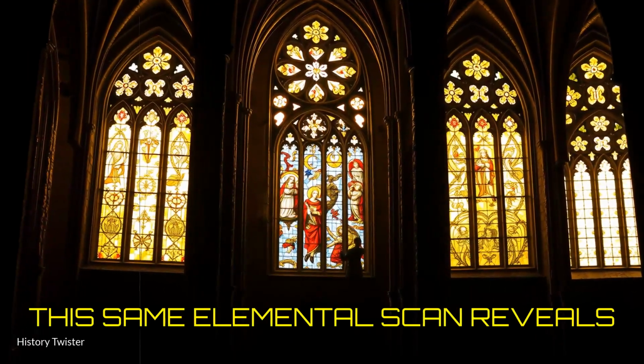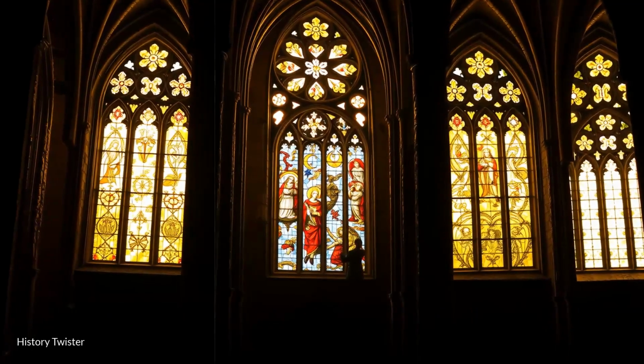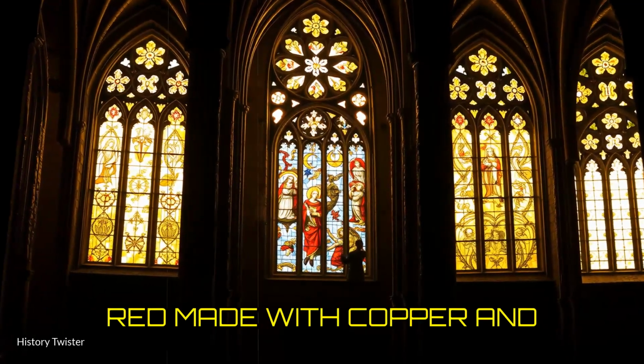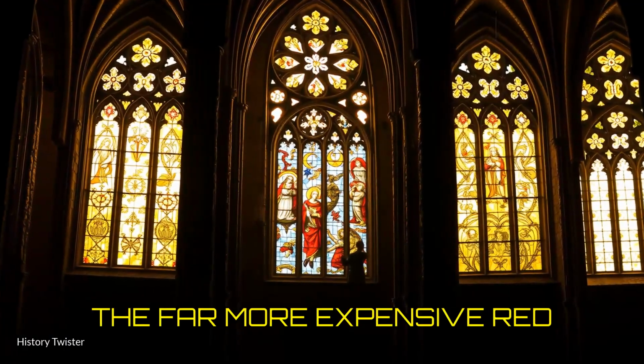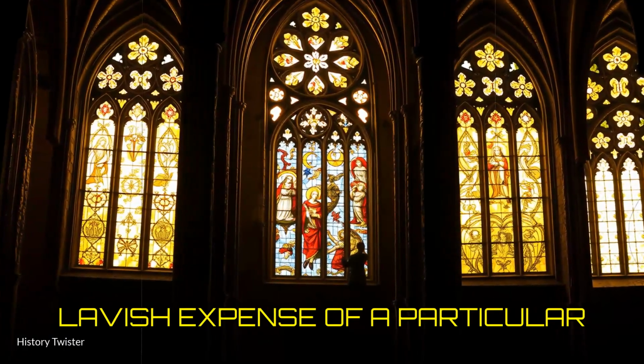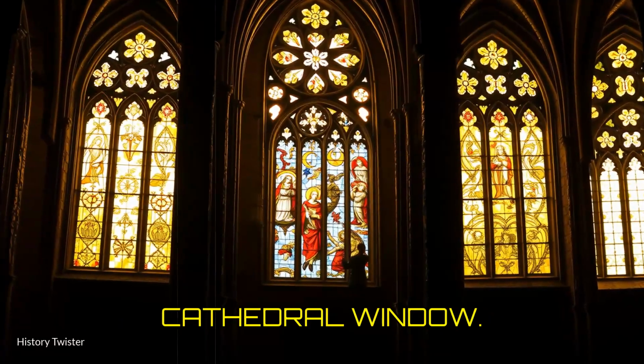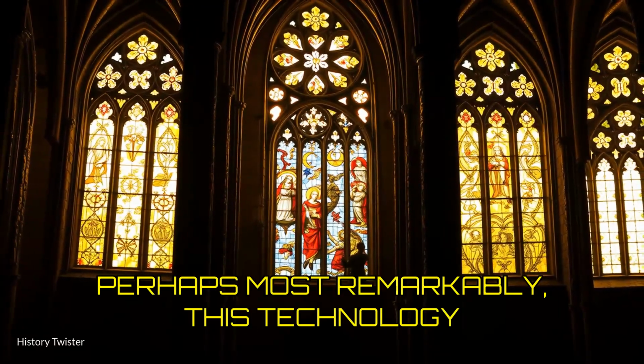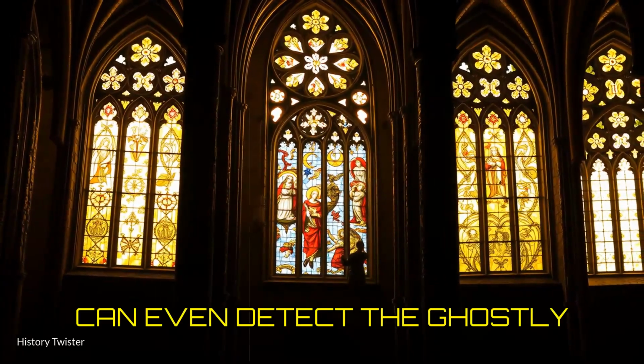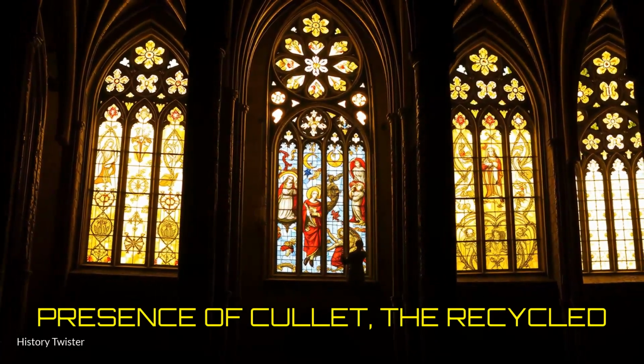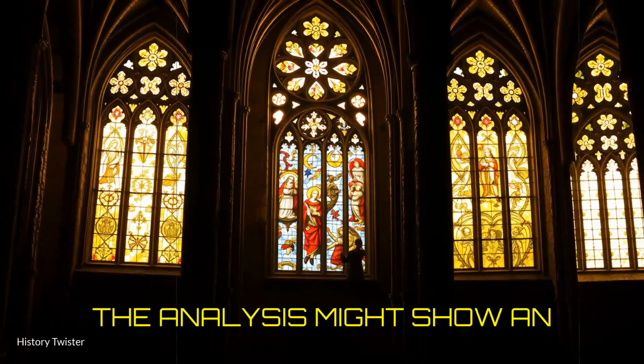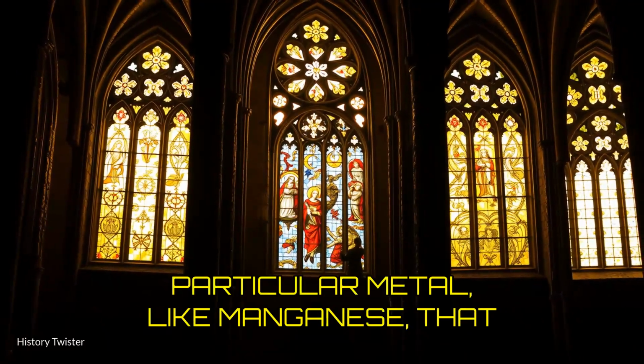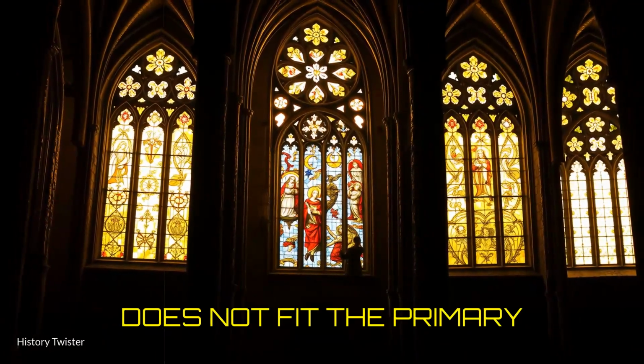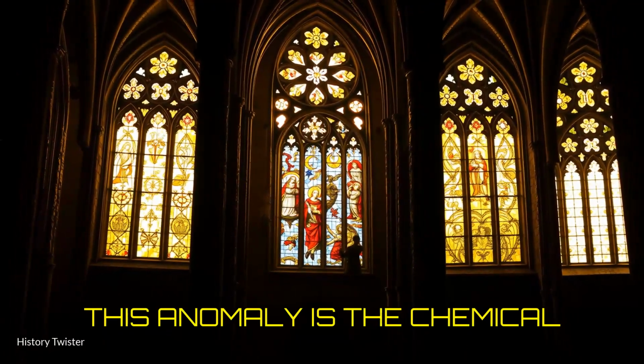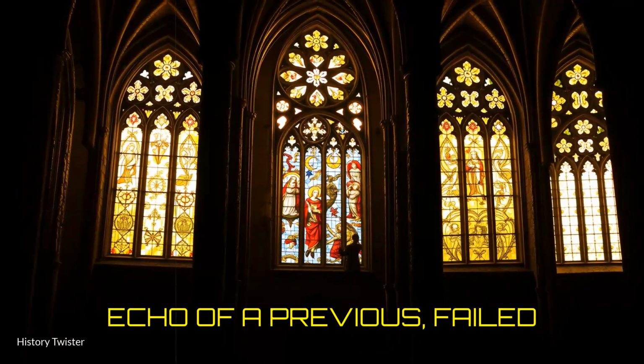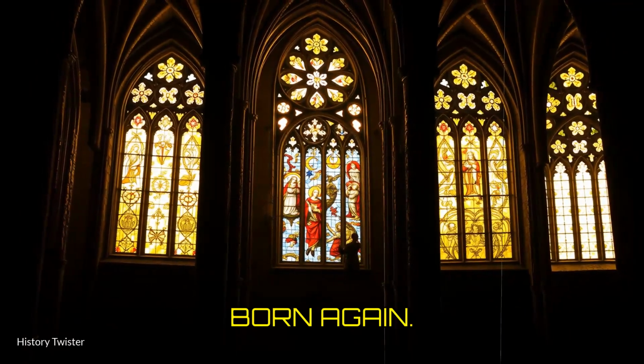This same elemental scan reveals the specific colorants a master used. It can distinguish between a red made with copper and the far more expensive red made with gold, confirming the lavish expense of a particular cathedral window. Perhaps most remarkably, this technology can even detect the ghostly presence of cullet, the recycled glass. The analysis might show an unusually high level of a particular metal, like manganese, that does not fit the primary recipe. This anomaly is the chemical echo of a previous, failed batch being melted down and born again.